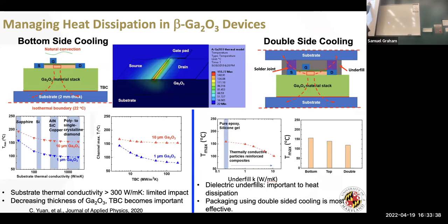The other thing is that this gray material that you see right here plays a large role in helping to pull the heat out. The technical challenge is that this material has to be a dielectric. It has to have the right breakdown properties, and it also has to have the right thermal conductivity. A lot of these underfill materials have good breakdown properties, but really low thermal conductivity. We want to push toward where you can see the temperature really start to drop. We're talking about 1 watt per meter K. If you can get above 10, then you really have something that could be integrated into these devices to help with that heat transfer. And of course I can also do double-sided cooling, cooling from the top and the bottom.